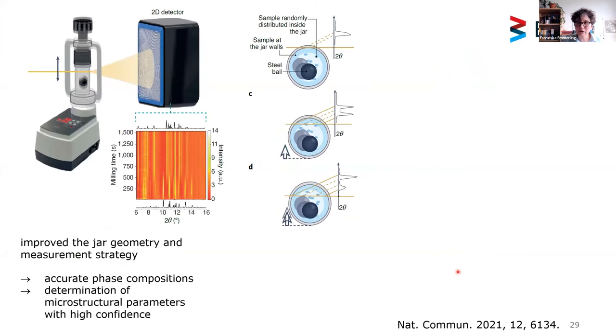I show you these data to highlight the changes we made to the in situ measurements with our new setup. We improved the jar geometry. So that is a jar that has a really thin wall now, so that we have not so much contribution of the Perspex material. And we also made changes to the measurement strategy.